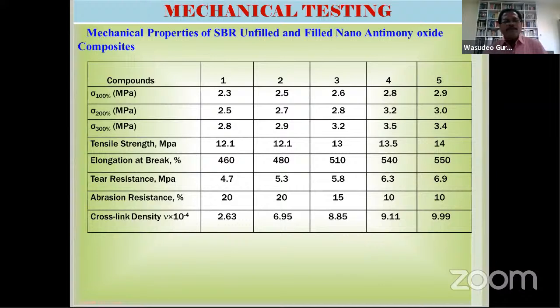And this is a very important table which shows some properties. Here tensile strength is shown, showing an increase, and elongation at break also increases, tear resistance also shows an increase, and abrasion resistance shows a decrease as the concentration of nanofiller increases. But cross-link density increases with the increase of nanofiller.